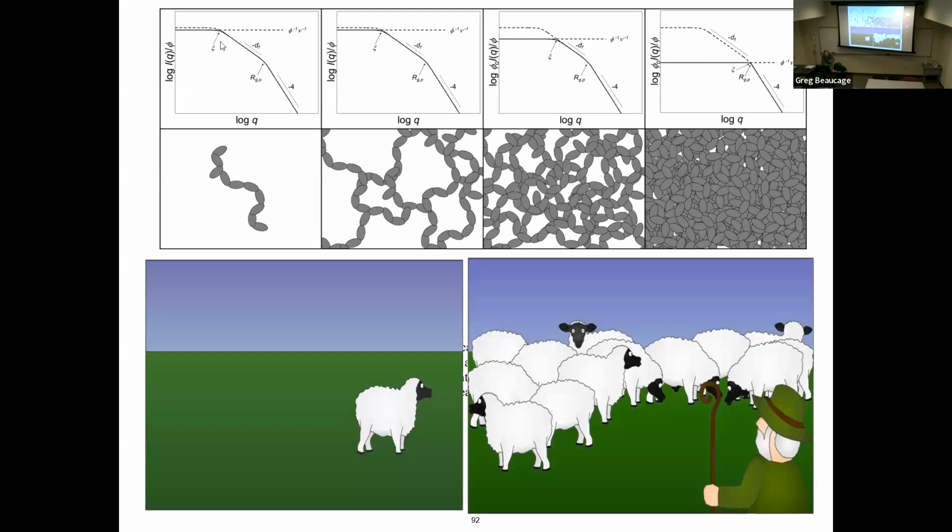So if you just have the polymer chains in solution, you have contrast like that, you can see power 1, you can see power 2, power 5/3 for good solvent, then 4. And then as you increase the concentration, you can't see the chain anymore. So that thing is gone, and then this correlation length shows up. And then that thing diminishes the higher the concentration. The rate of that diminishing is how well the fibers mix. So they can mix well or not well. If they mix not well, it drops slower. If they mix well, then it drops faster. Okay, so that's kind of the idea.